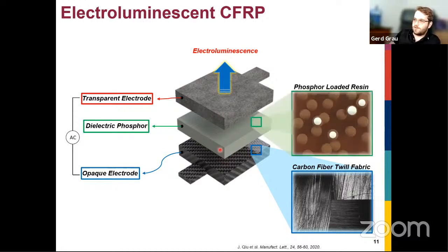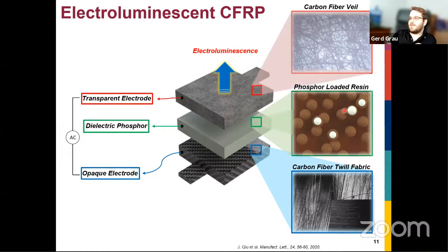The next layer, the dielectric phosphor, is the same epoxy we use to infuse the carbon fiber with, and it's loaded with these phosphor particles that emit light. We blade coat it. And then finally, the semi-transparent electrode is, again, carbon fiber. It's a veil. It's commercially available, so you can lay it up the same way as the other carbon fiber layers, infuse it with epoxy. It only lets about 50% of the light through, so that's a problem maybe, but it's all compatible. It's simple processes, so you can directly integrate it into a carbon fiber reinforced polymer process.